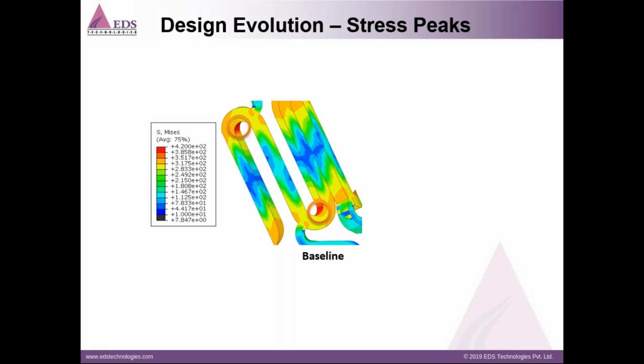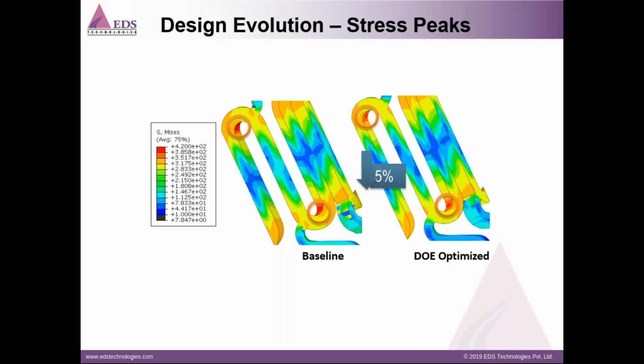So what result does it have, and how do you quantify the changes in the performance of the stent after the geometry has been optimized? In this contour plot, you can see the baseline von Mises stresses and some of the areas for which the stresses are peak or maximum stress. You can see it in some of the regions of the U shape. After the optimization, we can notice that the stress has been reduced by nearly 5% in those two regions.